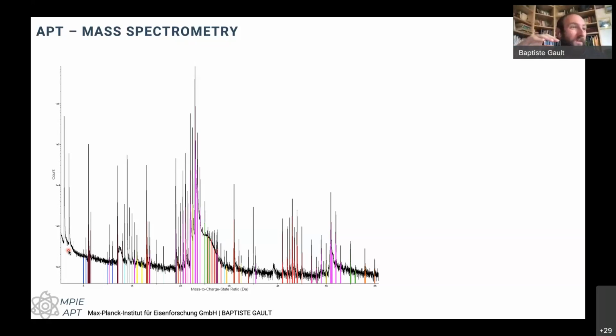So I think it really depends on what you're targeting when you want to look at hydrogen. So is it a hydride? A hydride can be analyzed like a carbide. It's going to have a small number of specific issues, but typically we can analyze it. So we've looked at quite a lot of hydrides in titanium or in zirconium alloys because they're fairly easy to form. So in Zirc, it was really quite interesting because it was a Zirc-4 alloy, so that contains tin. And we could see as hydrides were growing off from the grain boundaries that the tin didn't want to partition to the hydride, so it was actually being repelled away.